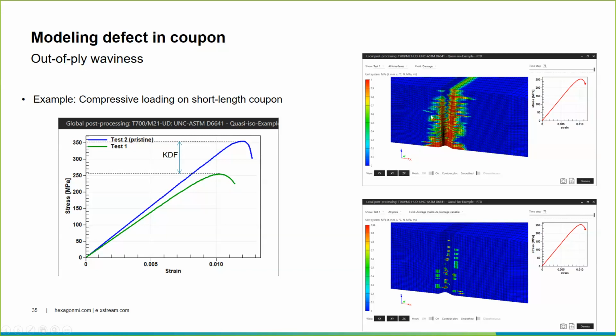We can also do the post-processing and identify the failure mode, and we see that for some quite severe waviness, the main failure mode is mainly delamination, with very little damage in the matrix here.